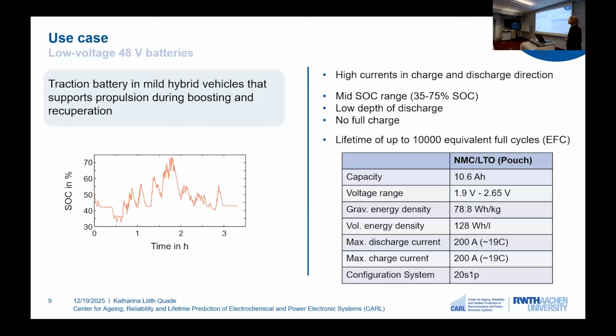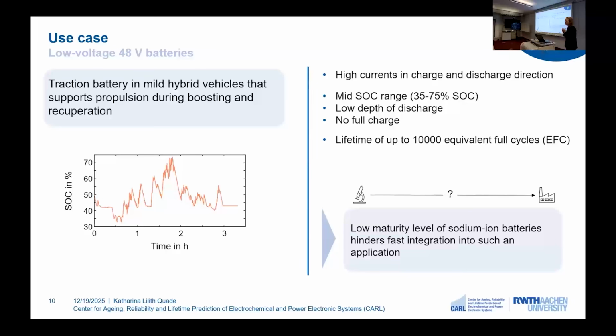In the original application, we use a costly NMC LTO cell with the following properties: capacity of 10.6 ampere hours, an energy density of roughly 80 watt-hours per kilogram, and very good current capabilities, as we can see here. And if we now want to replace the existing system with sodium-ion batteries, we need to account for the lower maturity level of sodium-ion batteries.